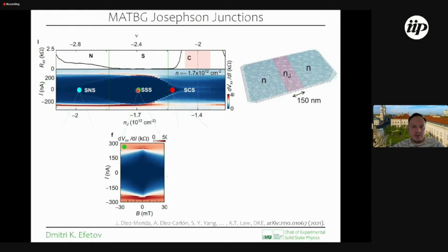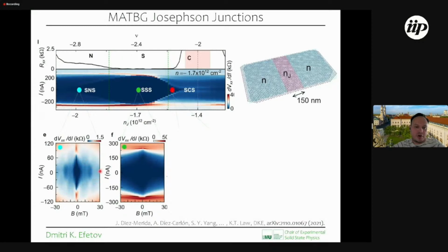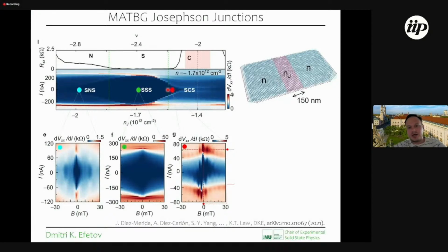However, if we now tune the central region to a normal state, so we form an SNS junction, we quickly start to see Fraunhofer interference patterns. So this is really a telltale sign that what we are doing is inducing a Josephson junction and basically separating the superconductor in the middle. But moreover, if we now tune the Josephson junction with the central region in the correlated insulator state, we can find a really strong superconducting Fraunhofer interference pattern, which is also very peculiar because, as you can see, it is somehow tilted. It's asymmetric with respect to the critical current and magnetic field directions.